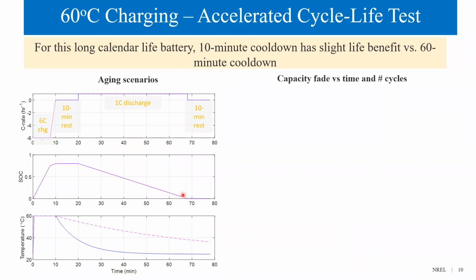Besides improving charge acceptance and lithium plating, elevated temperature will significantly impact battery life. To address this, a physics-based surrogate life model of a high quality, long calendar life commercial NMC graphite cell was used to analyze life benefits and detriments of elevated temperature fast charging. This commercial cell has a low calendar fade. Cells survive 1 year at 90% SOC at 60 degrees Celsius. Testing data include C/3 and 1C charge rates. We also include a cathode cracking mechanism and Arrhenius temperature dependence, without considering the lithium plating mechanism. As such, this 6C charge rate is a gross extrapolation, but it's still illustrative.